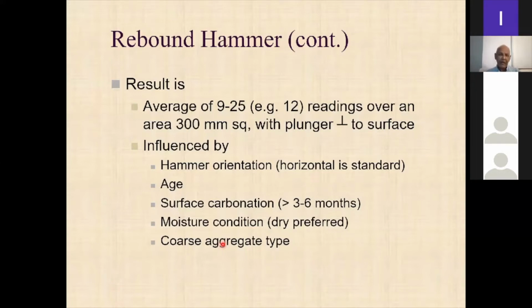That is why I am not happy when people say they have taken a set of rebound hammer readings, and they have used a calibration chart that is provided by the rebound hammer supplier. All of these things will be different, right? So actually, you should try to ensure that the surface is dry. But then, of course, you have to look at how old the concrete is and what the coarse aggregate type is. Hammer orientation, of course, we can rely on what the rebound hammer supplier says. But everything else will be different, right?